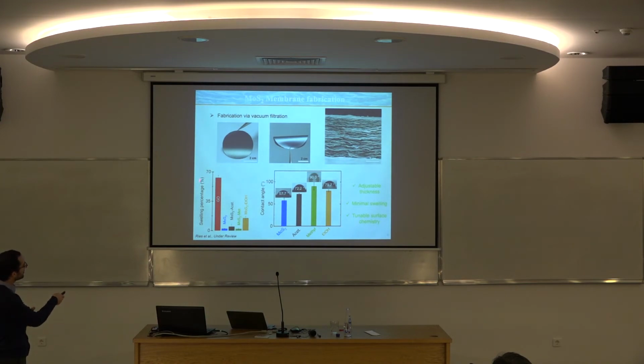And most importantly, we can also control the swelling. You see the swelling percentage of graphene oxide after 16 hours in water is about 65%, compared to 0 for MoS2, or close to 0. And in the worst case, I think it's around 15% for ethanol functionalized MoS2.